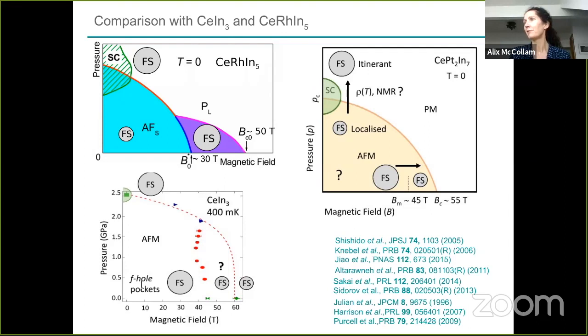Yeah, by finite extent of certain phases, you mean just the accessibility of these phases? There are problems in being able to measure. You need extremely high crystal quality to be able to be sure that you're actually measuring all of the Fermi surface and being able to resolve it. Also, you mean perhaps as a function of temperature. So you need to measure the effective mass in quantum oscillations by measuring the temperature dependence. And if you have a limited temperature range over which you're in a certain phase, then indeed you can come into trouble. So if you have to measure your temperature dependence across a phase boundary, then it's difficult. So you have to do the best that you can. Yeah, the masses, even the ones that are not most strongly renormalized, are still quite heavy.